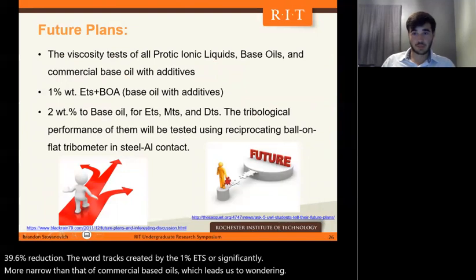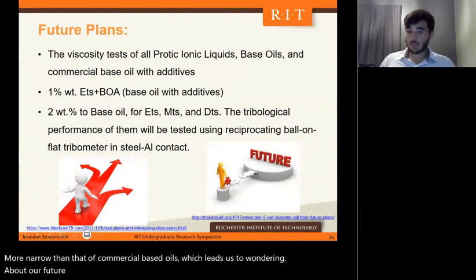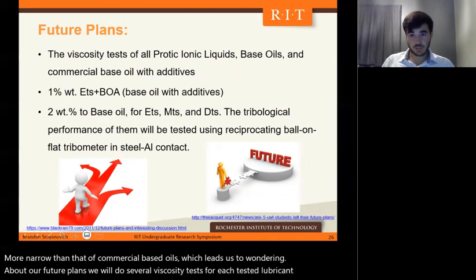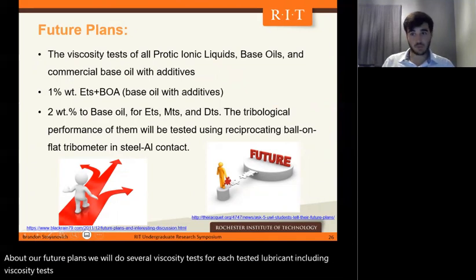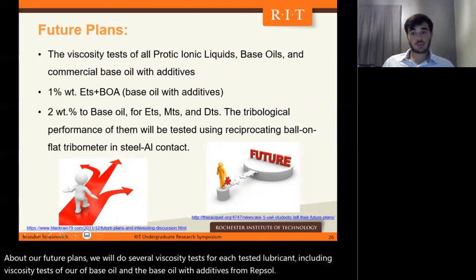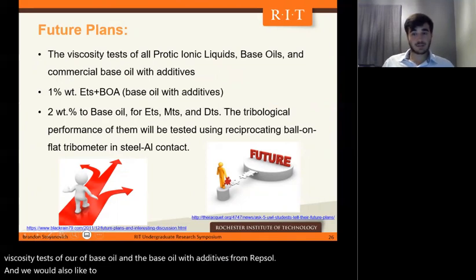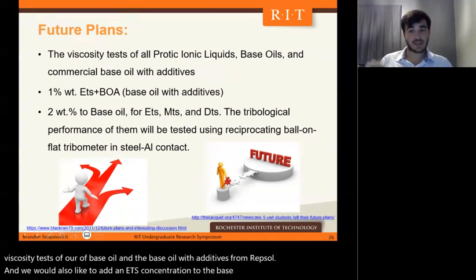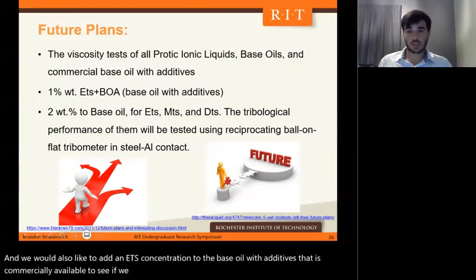about our future plans. We will do several viscosity tests for each tested lubricant, including viscosity tests of the base oil and the base oil with additives from Repsol. And we would also like to add an ETS concentration to the base oil with additives that is commercially available to see if we can yield synergetic effects in terms of coefficient of friction and wear.